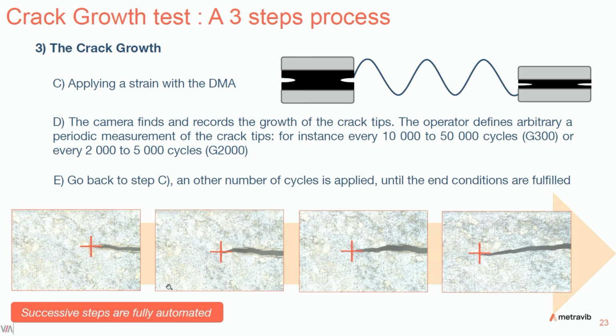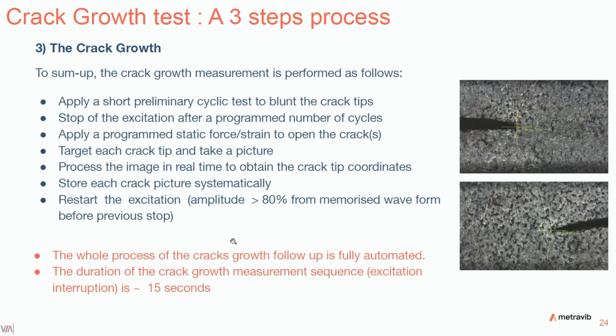These successive steps are fully automated. Just to sum up, crack growth measurement is performed as follows. Apply a short preliminary cyclic test to blunt the crack tips. Stop the excitation after a programmed number of cycles. Apply a programmed static force or strain to open the crack. Target each crack tip and take a picture.